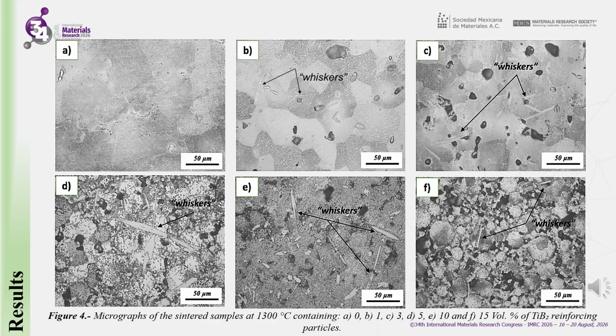As illustrated in Figure 4, the micrographs of the sintered samples reveal the presence of a distinct phase. The composites containing 3, 5, 10, and 15% by volume of titanium diboride exhibit the formation of whiskers in their microstructure generated by the reinforcing particles in the matrix, in addition to the presence of the equiaxed grains of the alpha titanium phase in all samples.